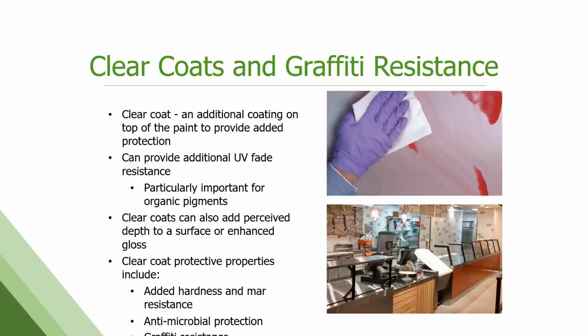So the clear coats and graffiti resistance, these are quite fascinating. So the clear coat goes on top to provide the added protection, either to help with UV fade resistance, or corrosion, but also to help with graffiti, right? So some of the new clears that are out there, it's really hard to get any other coating to even stick to them in the first place. And then if something does stick, they're very easy to clean and get that graffiti off.